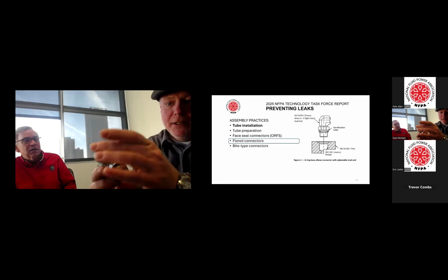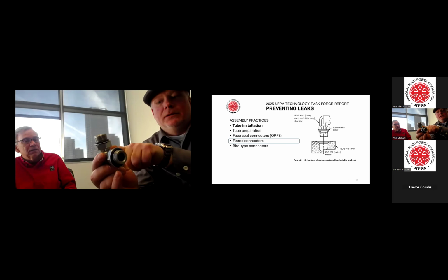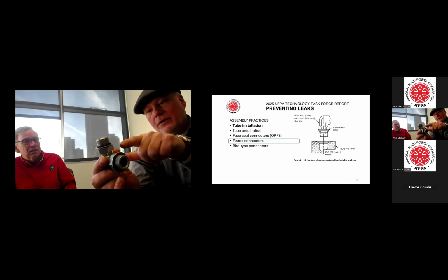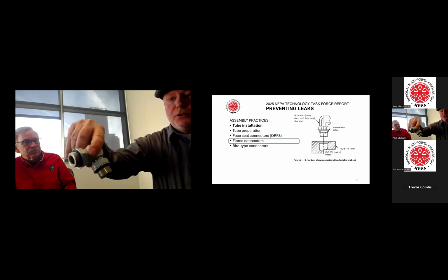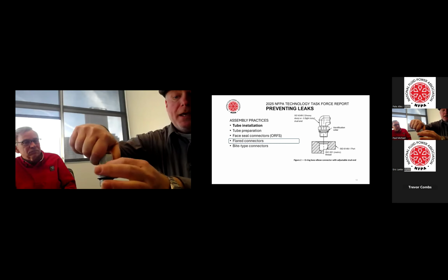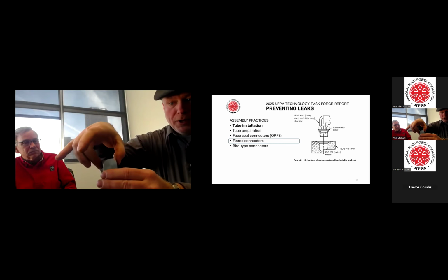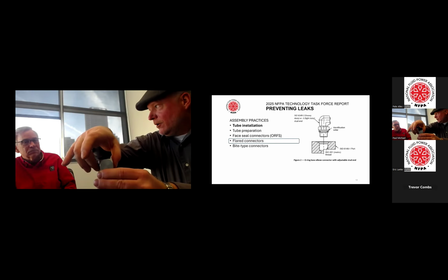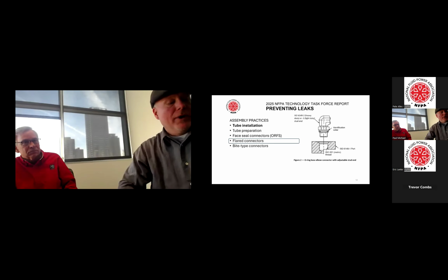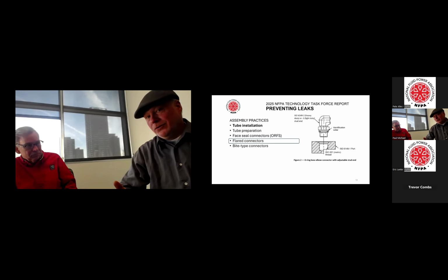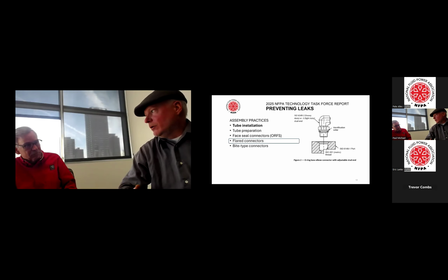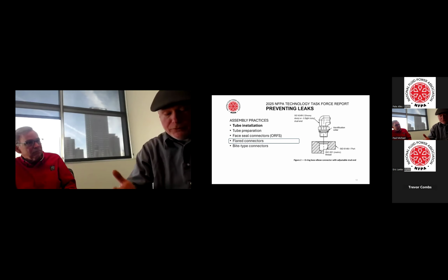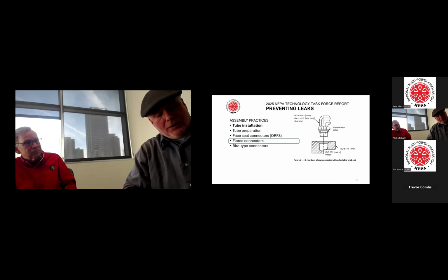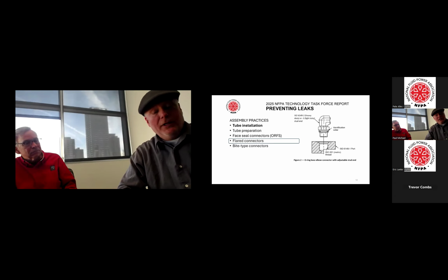Again, hand tighten this down, and then 360 degrees, once that O-ring is seated, you can adjust to turn, and then tighten your jam nut, holding your fitting. So you're not grinding that O-ring, because a lot of people don't use lubrication on their O-rings, which they should put a little bit on when they assemble, but they don't, they should. So it goes together without leakage.